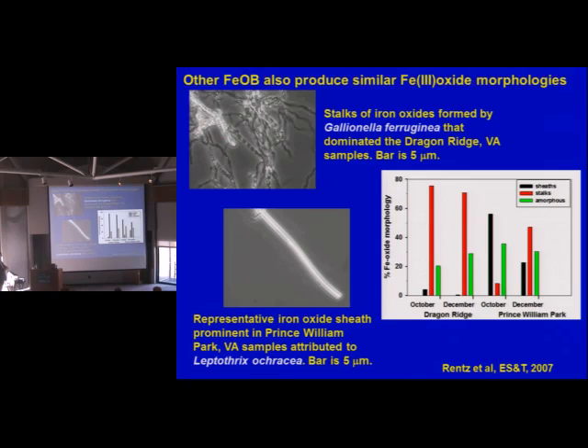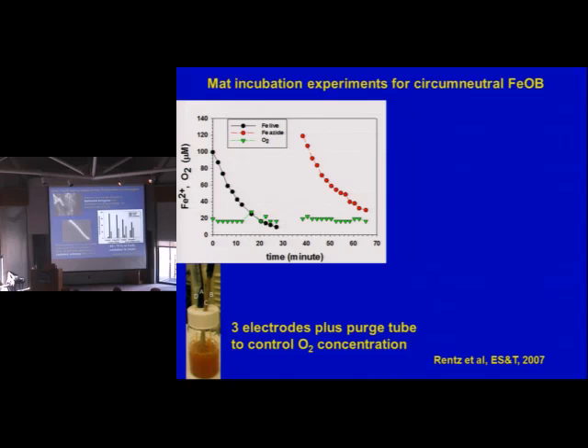Notice that the amorphous is relatively the same between these sites. pH was about the same. So it's a matter of what's the concentration or number of cells per milliliter that's going on, because we just took the mat. So in this case, 65 to 75% of the iron 2 oxidation was biotic. When you started adding all this up, just from that kind of data, that's even better than what I showed you in the monoculture. So this is actually in the field.